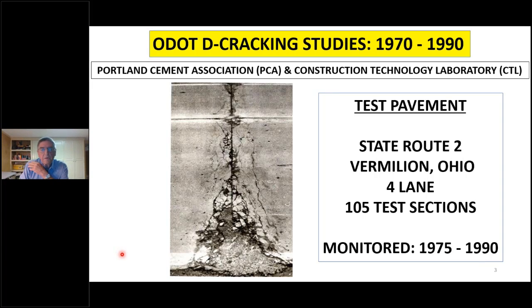This is a review of the D-cracking studies that were conducted. PCA at the time, Portland Cement Association, became CTL, Construction Technology Laboratories. That work was done for ODOT. This of course is a photograph of a severely distressed joint on one of the Ohio pavements back then. At the end of the studies in the 70s, a test pavement was constructed on one of the state routes around Vermilion, Ohio. It's four-lane with 105 test sections. And that was monitored over that period, 75 to the early 90s.